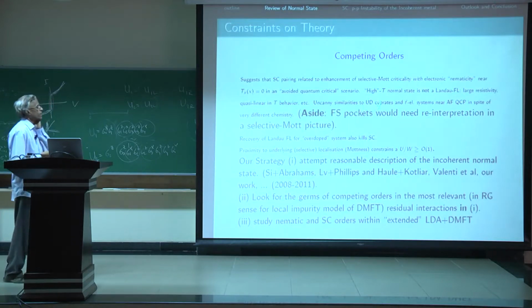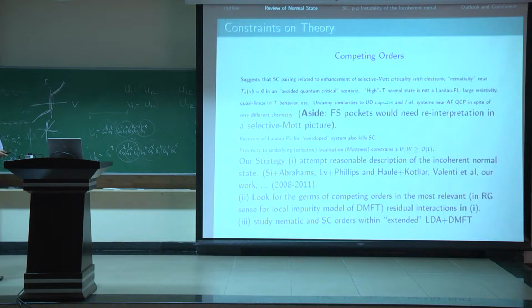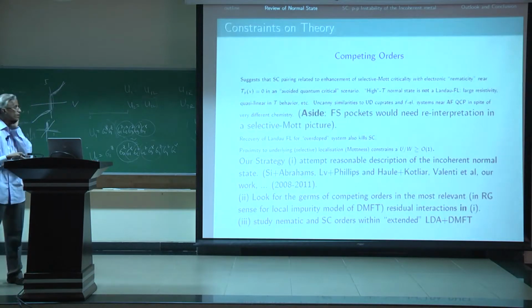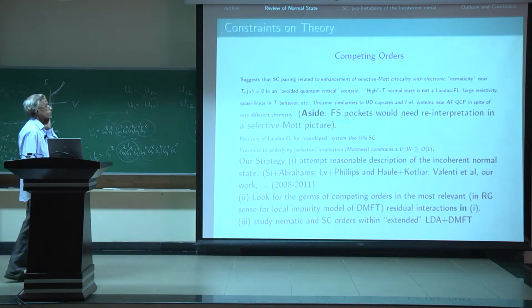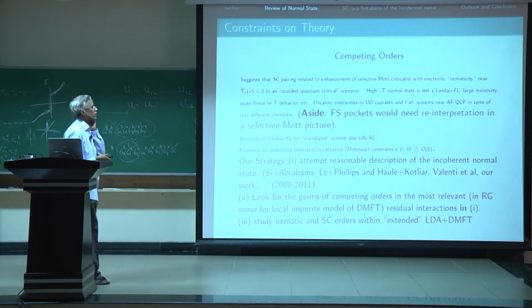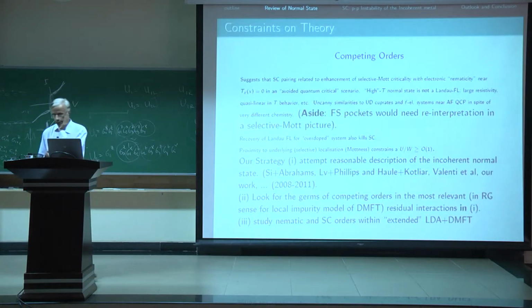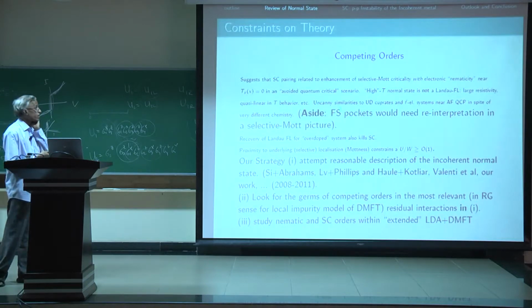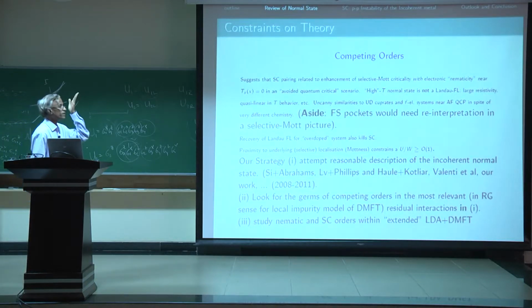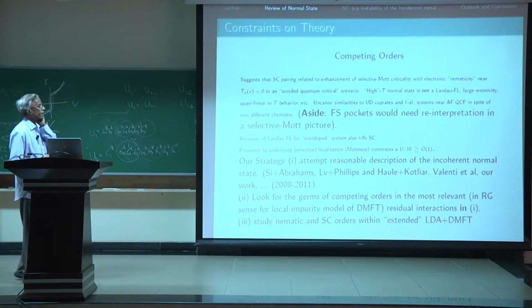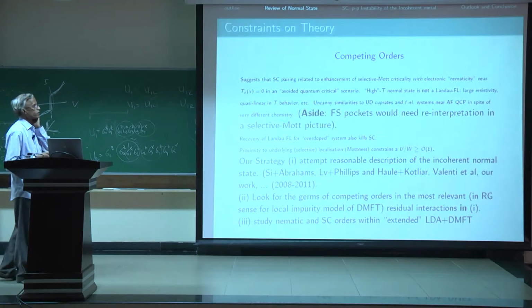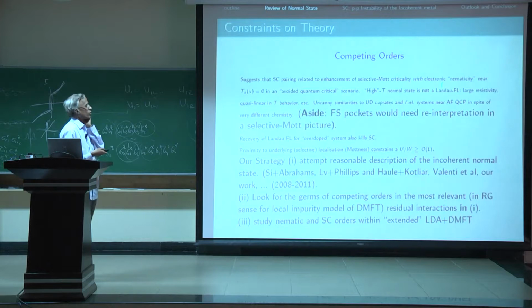So an important consequence of all this is basically that in a selective Mott critical picture, since a subset of the Fermi surfaces are basically eaten up from the unperturbed band structure, the resulting magnetic instabilities would basically need a reinterpretation, since one would not expect the nesting, which was seen in LDA calculations, to persist when the Fermi surface reconstruction occurs in the sense of selective Mott.